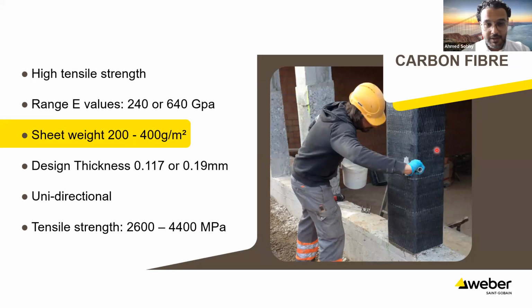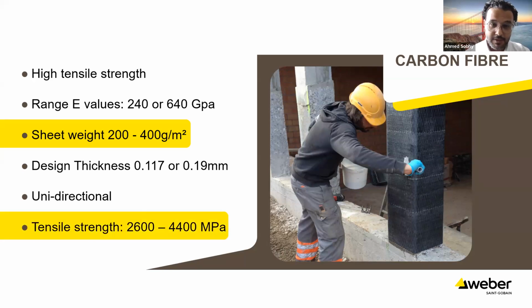If we talk about the mechanical properties, we're talking about a sheet weight of around 200 to 400 grams per square meter. Obviously, this is a very low weight, especially compared to our regular day-to-day material that we use in construction. We're talking about a tensile strength of about 2,600 to 4,400 megapascals.